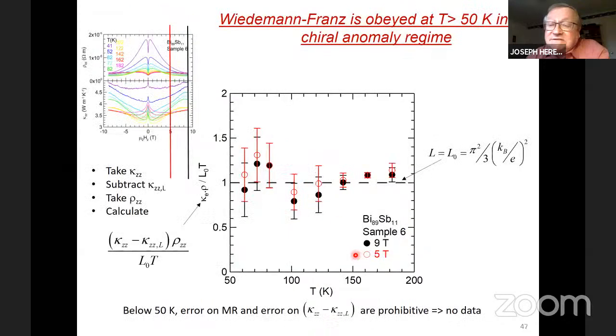We do that here. So at two magnetic field values of 5 Tesla and 9 Tesla, you take the points for various temperatures. You subtract the lattice, which of course adds to the error bar as I have shown before. And you multiply by the resistivity. You then divide this by the free electron Lorentz ratio and temperature. And you get the data points that I show here for the two magnetic fields as a function of temperature. So to verify the Wiedemann-Franz law, you really need to verify two things.